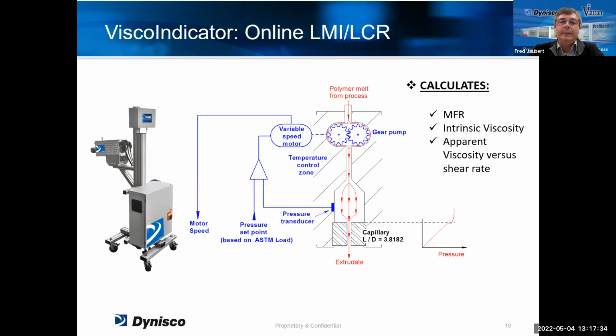And one example of this is a product we have developed called the ViscoIndicator, an online LMI/LCR. The process of operation is slightly different in this case, but it's still pretty close to what we use in a capillary rheometer. Instead of having a piston pushing the material through a capillary, as you see here, we have a gear pump which, depending on the speed, generates a flow of polymer and an increased pressure.